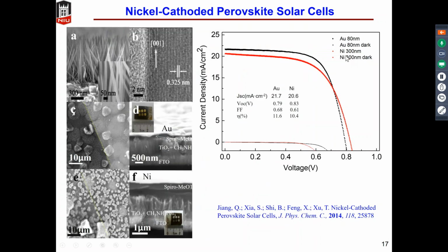And you also notice that for nickel, you have to coat a much thicker layer because nickel has a relatively lower conductivity than gold. So if you coat less than 300 nanometers, the cell will suffer from high series resistance, so low fill factor. And this work actually attracted some attention from the financial field. Yahoo Finance reported on our work, quite surprisingly. Maybe the Wall Street people always try to sell nickel at the price of gold.